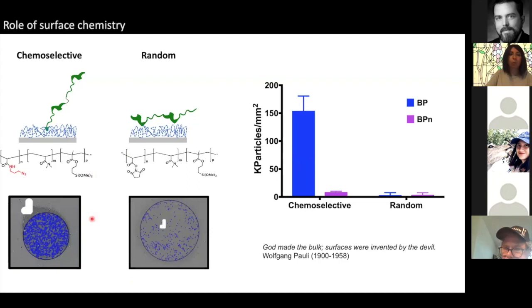You can see here how many vesicles we can capture using this polymer, and how poor is the binding when we use this other random polymer. And this is the difference if you look at the number of kiloparticles in the chemoselective versus random chemistry. So this is to underline the role of surface chemistry, how important it is to carefully tailor the surface when you use peptides, which you have to imagine are very small molecules compared to these big balls that are the vesicles that are captured and sitting on the surface.